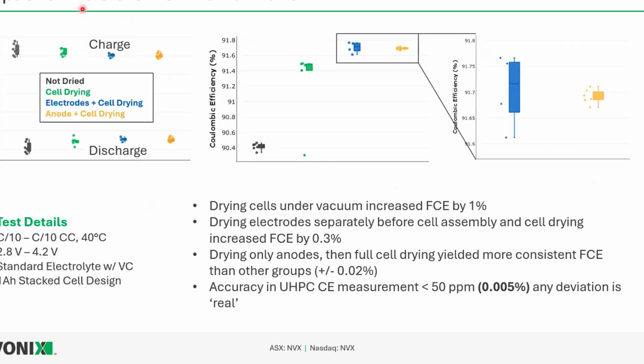So I'm going to show some formation data, and all of this formation was done on our UHPC cyclers. So you can see here the differences between charge and discharge, and these statistical diagrams are very nice to show the consistency of the cell builds, and then how this translates into Coulombic efficiency. And you can see all of these cell builds are quite consistent with really tight tolerance on Coulombic efficiency. And you can really see the effect here of not drying the cell with a lot lower of a Coulombic efficiency, almost a % difference.